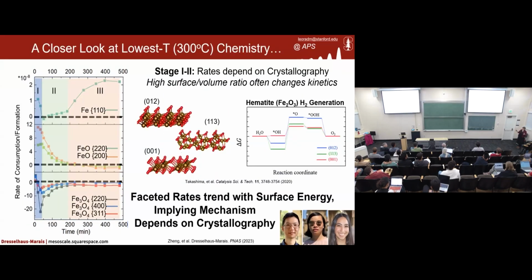So when we look at this and we see how actually in the first two stages, there's very strong dependence along the crystallographic direction. You might say, wow, this must mean something really weird. But actually, this is well understood in the field of nanoparticle catalysis that, in fact, when you have so much of your material as surfaces, the type of surface matters a lot. And so, in fact, this correlates very nicely with the classical catalysis literature, which nicely validates for us that these mechanisms are going exactly as you would expect.